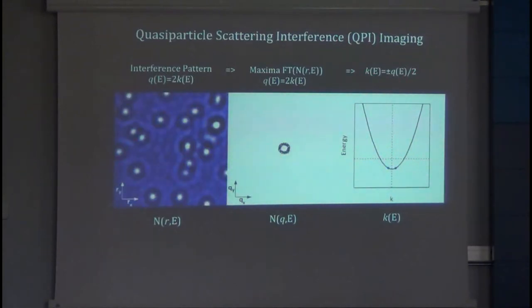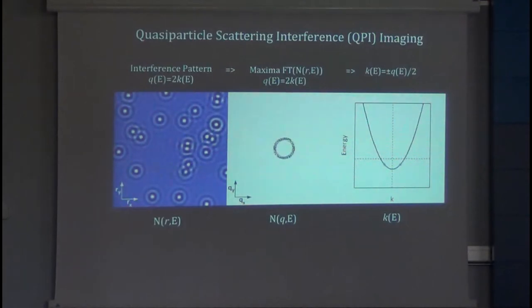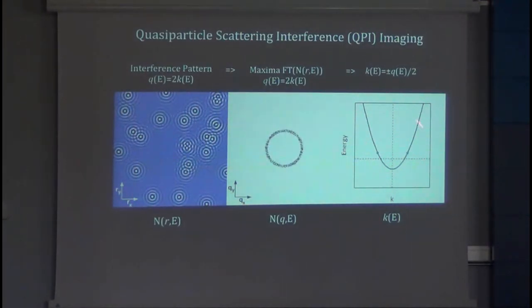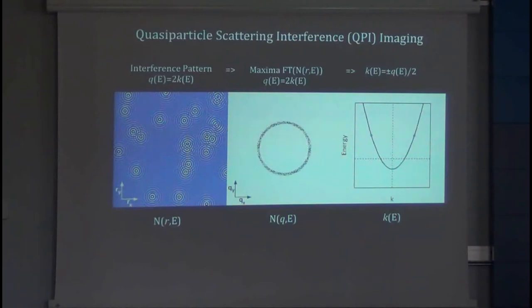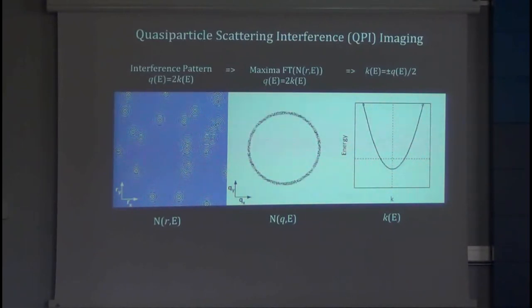And then if you do this as a function of energy, you can map K as a function of E for the delocalized electrons in the material. This is really cool. And with apologies to any photoemission colleagues in the audience, it's better than photoemission for two reasons. One is we can see all the states above the chemical potential as easily as the states below. And secondly, we can do this experiment at temperatures down to 10 millikelvin, so we can get rid of KT from the spectral function.